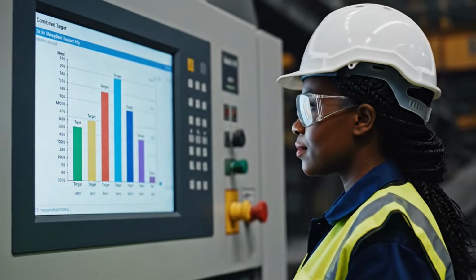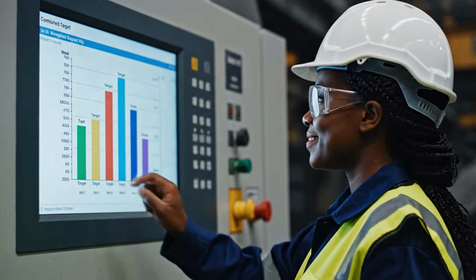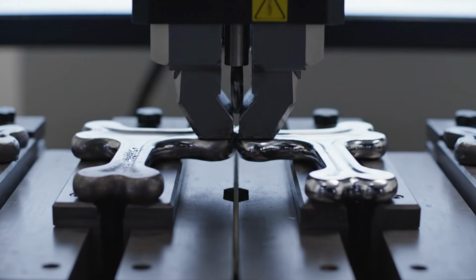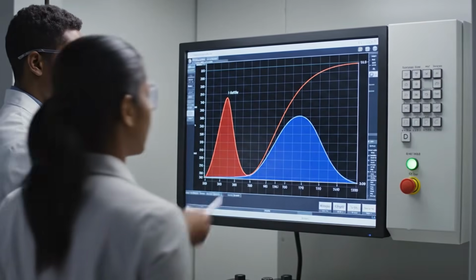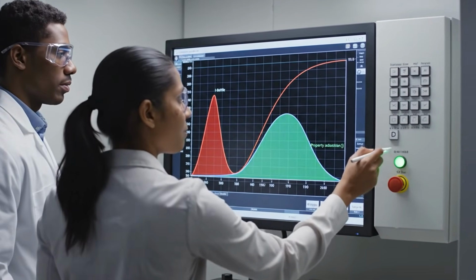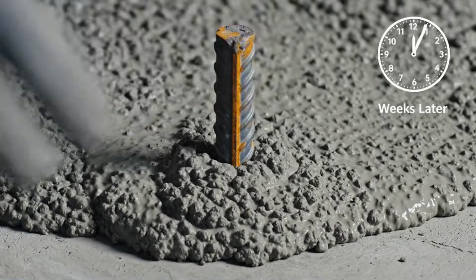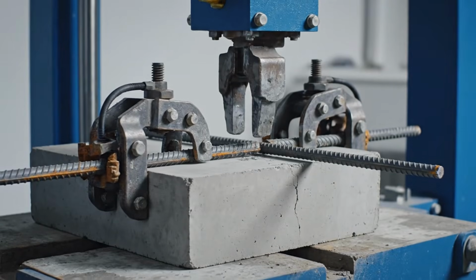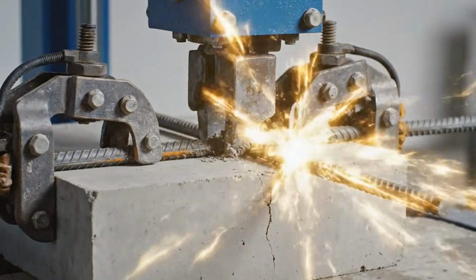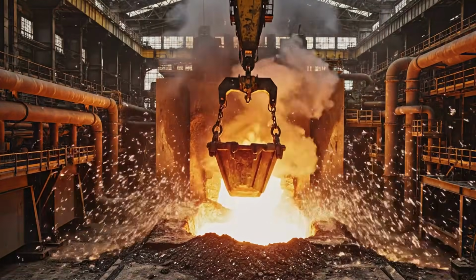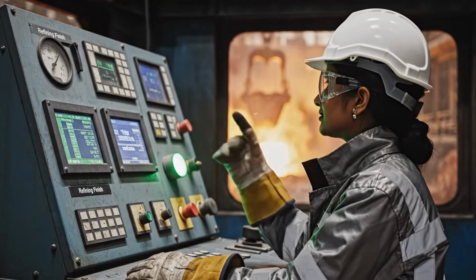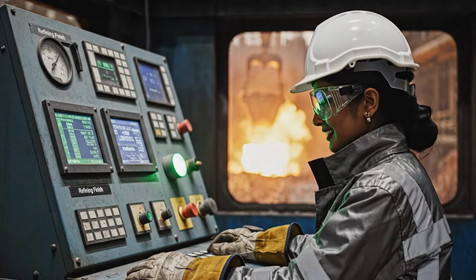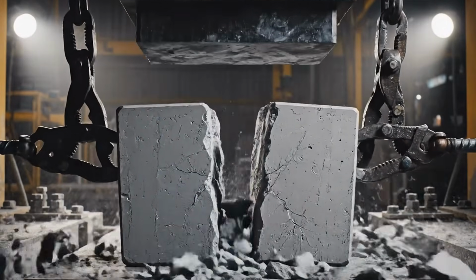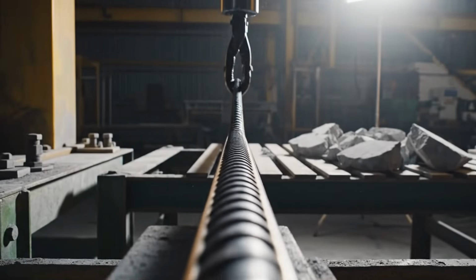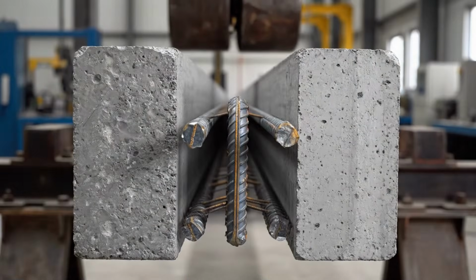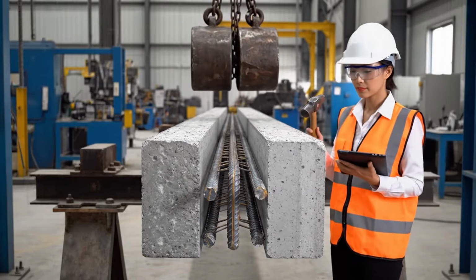Slag plays a key role. It floats on top of the liquid steel and acts as a protective and purifying layer. Many of the residues that would weaken the final material remain trapped there. At the same time, operators and control systems add ferroalloys in calculated quantities to precisely adjust the chemical composition. Manganese, silicon, and other elements allow for the modification of hardness, mechanical strength, and the behavior of the steel during rolling and subsequent cooling. All this metallurgical work has a very clear objective: to produce a steel that is not only strong but also compatible with reinforced concrete.